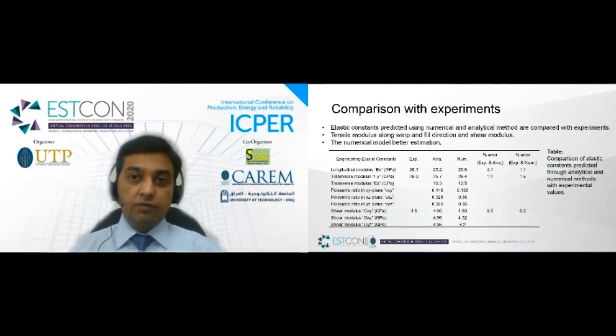The elastic constants of 3D composites predicted using multi-scale homogenization are compared with in-house experimental results. The experimentally determined tensile modulus along warp and fill direction and shear modulus are compared with the predicted values. The numerical model shows better prediction as compared to the analytical model because it can accommodate more geometric variabilities and actual boundary conditions. The finite element analysis of 3D composites at macro scale requires all the 9 engineering elastic constants, so the main purpose of this work is to predict these elastic constants and to reduce the number of tests.